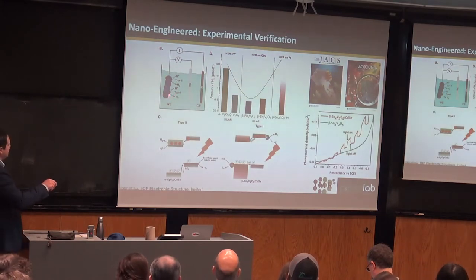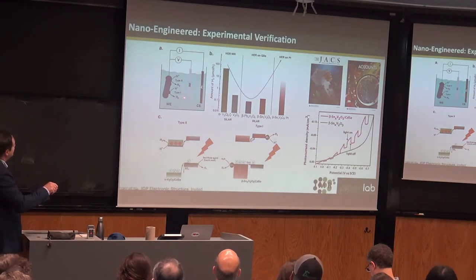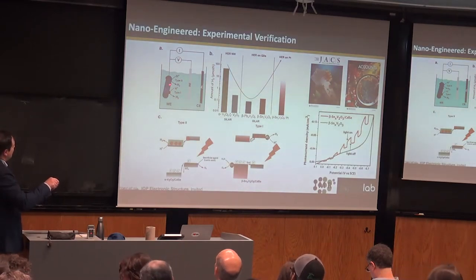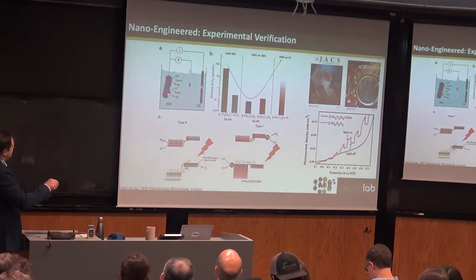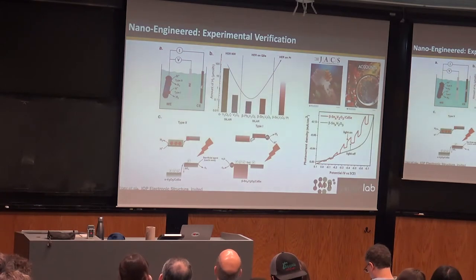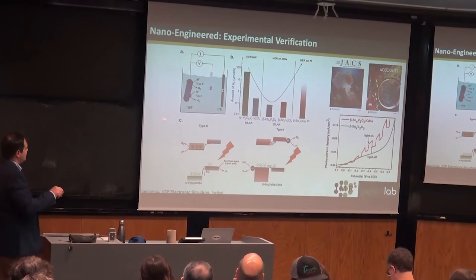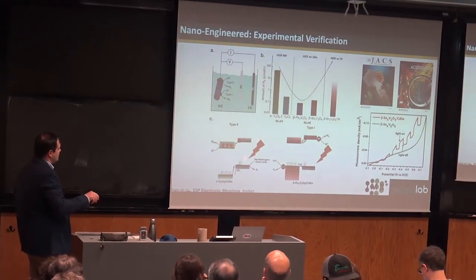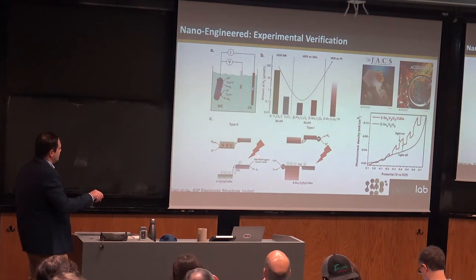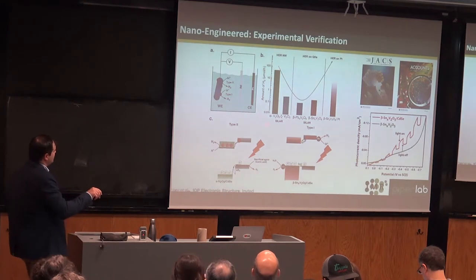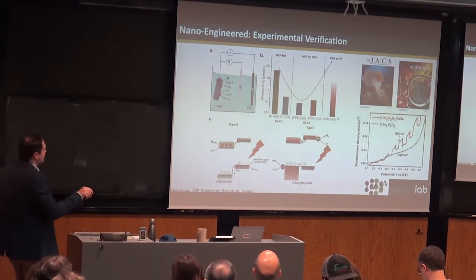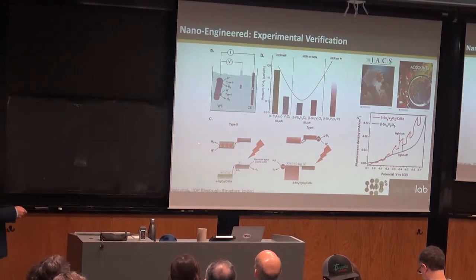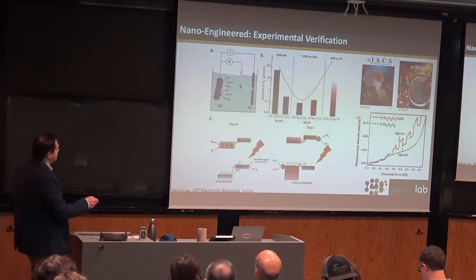So this is a diagram showing that we could have two different arrangements. We could either have the hydrogen evolving on the nanorod, or we could have the hydrogen evolving on the quantum dot. We want it on the quantum dot. In the case of the V2O5, because the valence band offset is like this, with these photocarrier excitons, you get a situation where your electrons transfer here and you have a buildup of holes, so we usually put a sacrificial agent in on that side. But on this side, you actually get the hydrogen evolving component. As we change the polymorph, remove that split-off band, that seems to be important for localizing charge in order to facilitate the catalysis. And so in that case, we see a reduction of hydrogen.